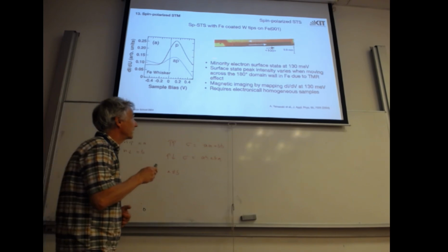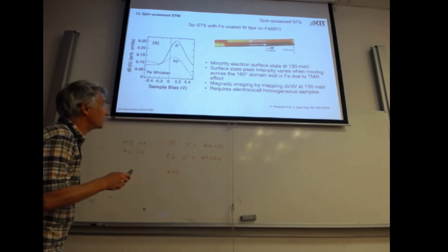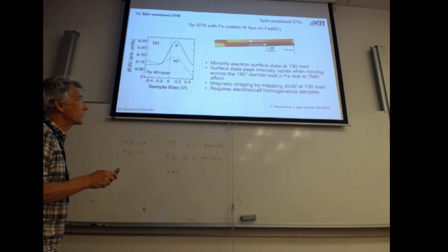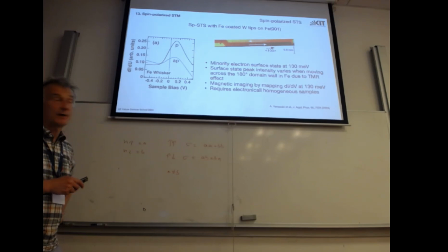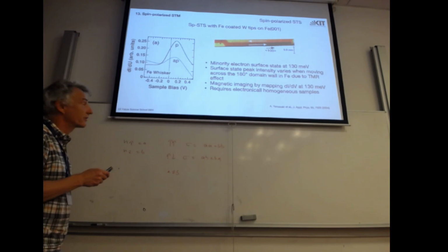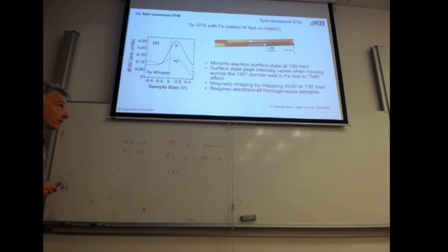So we distorted the lattice, which causes a problem, but you can park your magnetic tip here and here, and without changing anything, just go from this domain to that domain, and you can see the difference in the tunneling current. We call it the differential conductivity, and there is actually a minority surface state in iron at around 130 millielectron volts. For parallel, we get a large surface state peak, which is spin polarized, and for anti-parallel, a weak one. So this you can map.